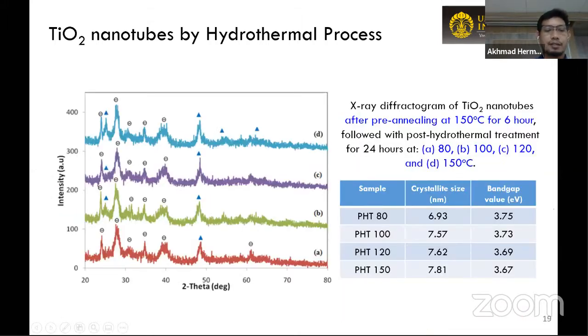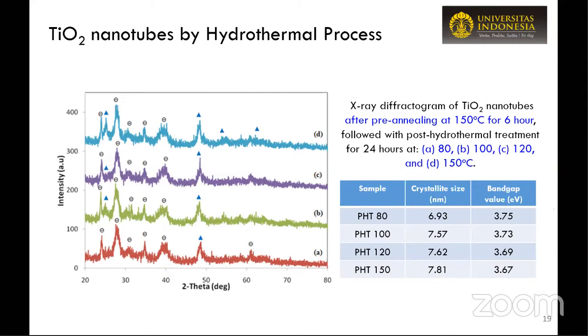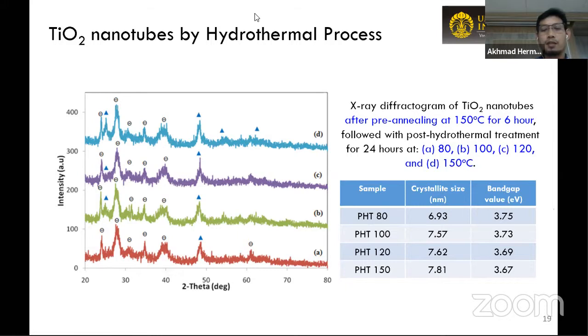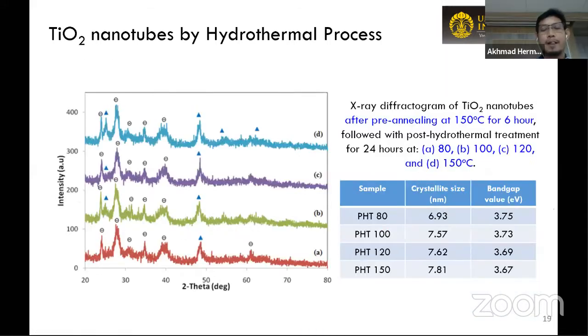This is the result of the X-ray diffraction. We can see here that A is the nanotube that has been subjected to 80 degrees Celsius, B for 100 degrees, C 120, and D 150. But remember, before we subject to post-hydrothermal treatment, we have done the pre-annealing at 150 degrees Celsius for 6 hours, to make the nanotube strong enough before being attacked by the water at high pressure. We can see that here the crystalline size can improve, although maybe it is not as large as with the result of the conventional annealing, but the improvement is quite satisfying.